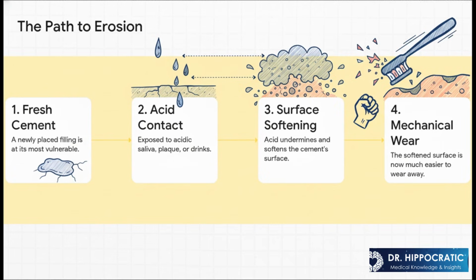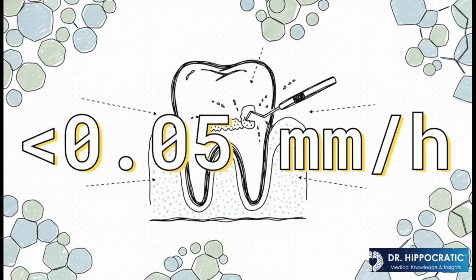It's a devastating 1-2 punch. Chemical weakening followed by rapid mechanical breakdown. Now, this problem is so significant that it's actually regulated by an international standard. The rule sets a very, very specific limit. A GIC filling is not allowed to lose more than 0.05 millimeters of its surface per hour when it's exposed to acid. That's a tiny number, which shows you how serious this is.